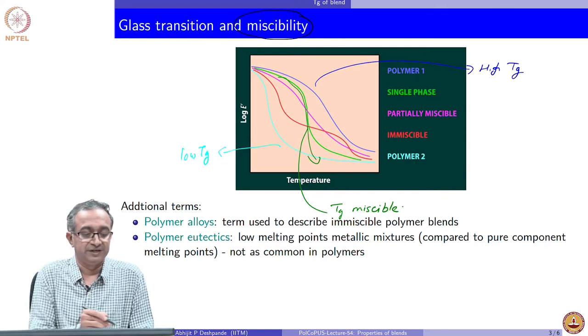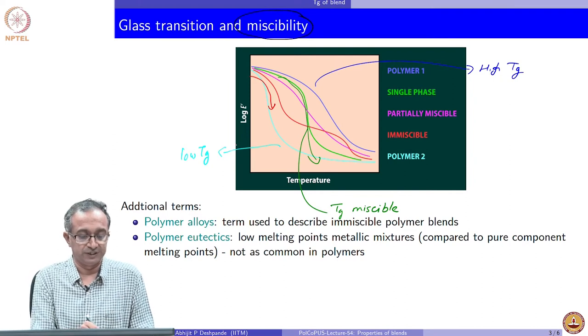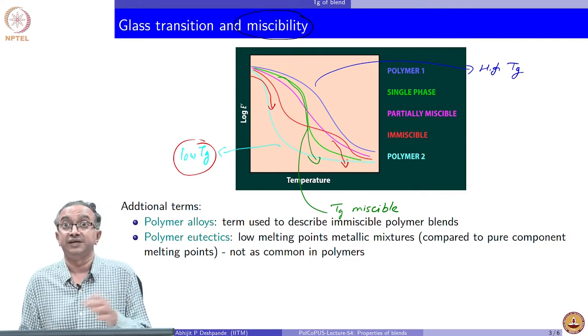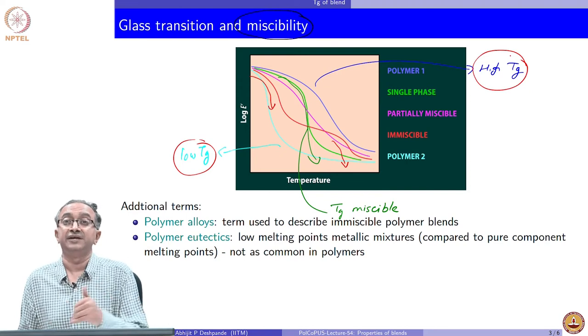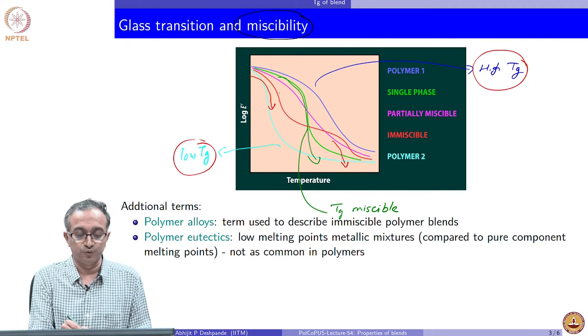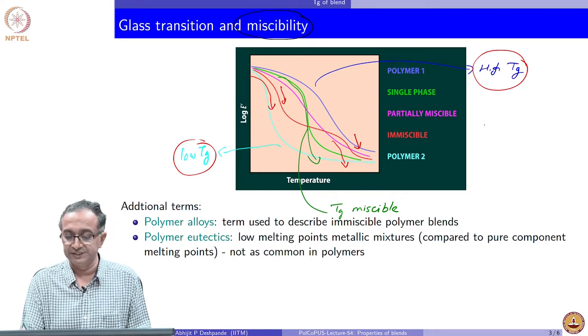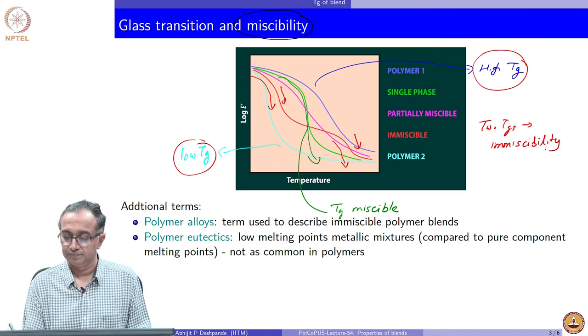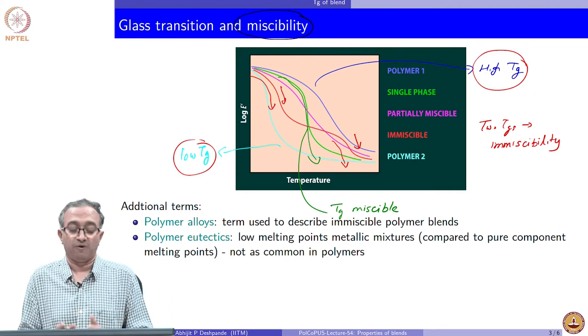On the other hand, if they are immiscible, then there will be a decrease associated with segmental mobility changing for one polymer, which is the low Tg polymer. If we increase the temperature further, we will observe another decrease in the E prime because segmental mobility again increases, but this time of the polymer which has a higher glass transition and again E prime undergoes a change. Therefore, these two steps indicate that we have an immiscible blend. Two Tg's imply immiscibility and in between, if they are partially miscible, then we can have more complex variation also.